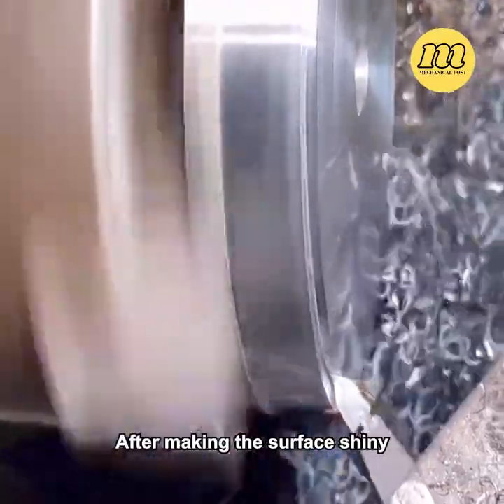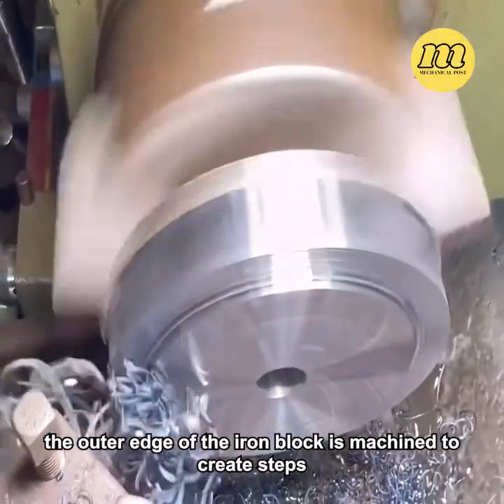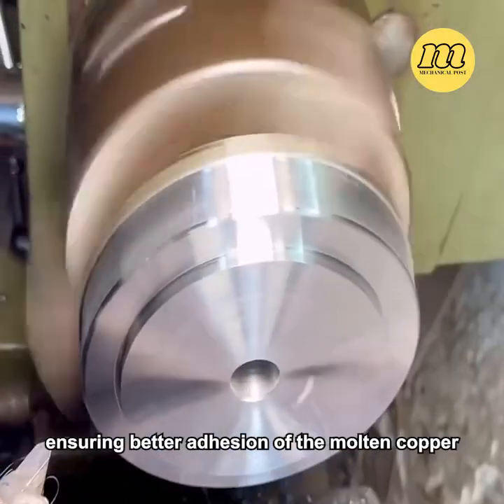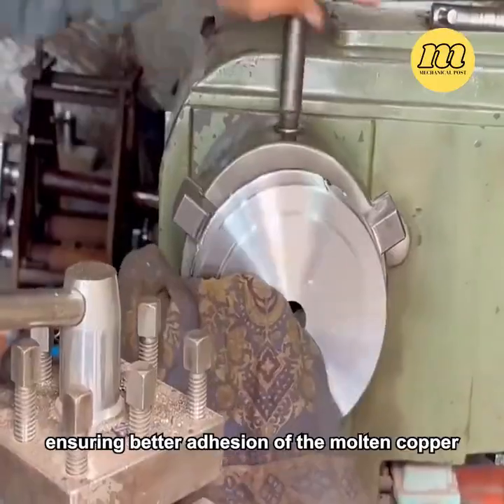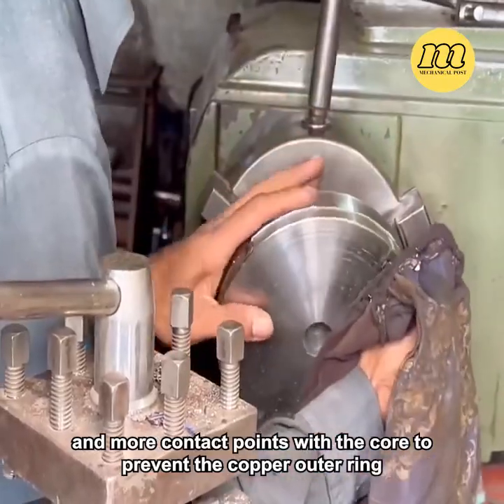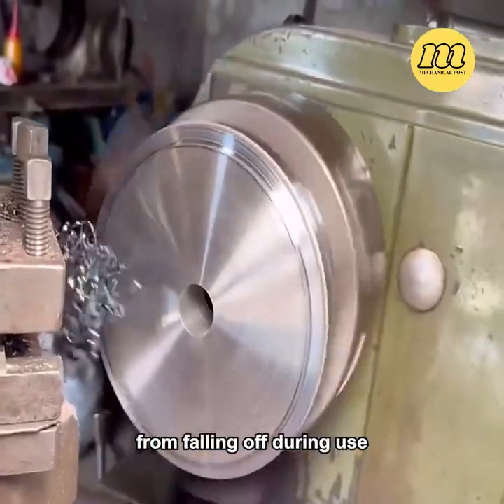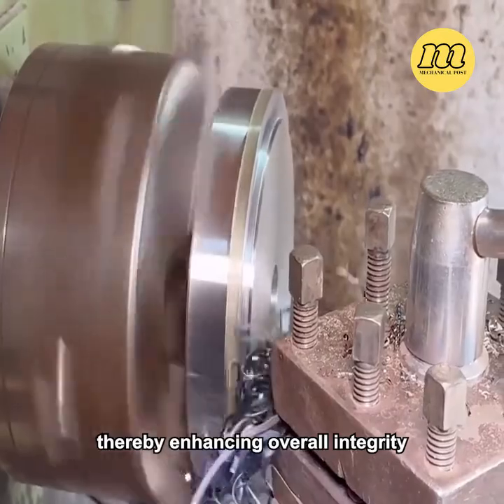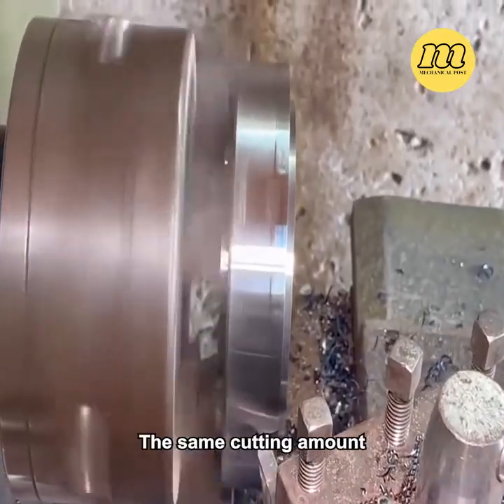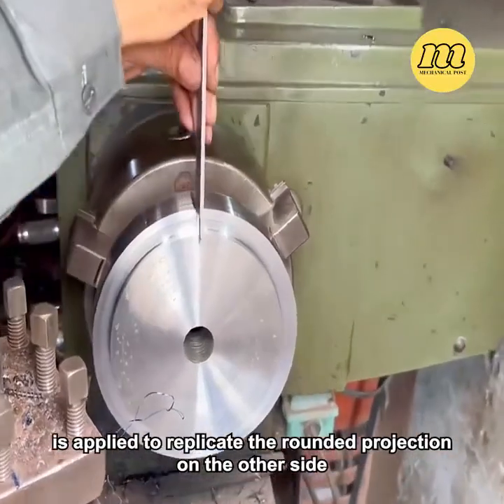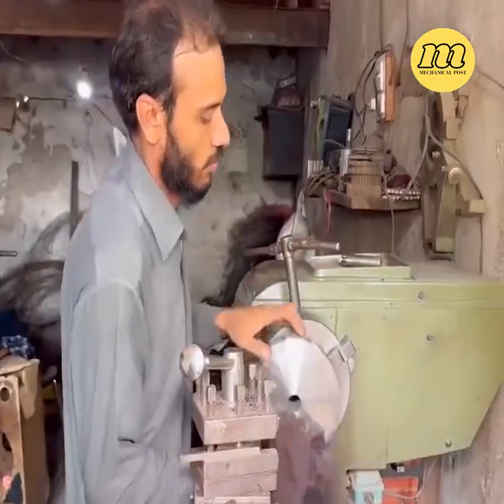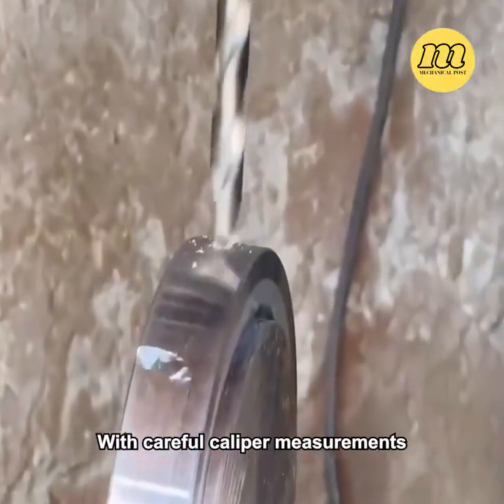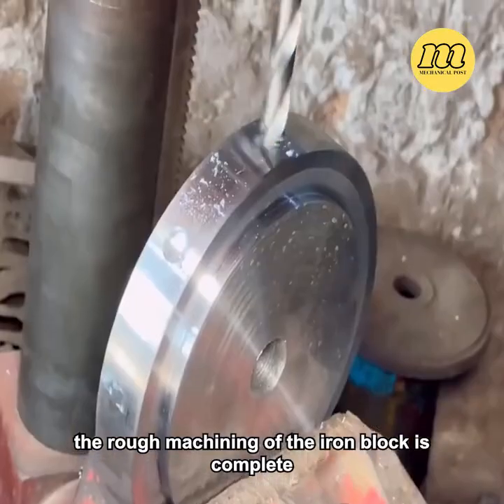After making the surface shiny, the outer edge of the iron block is machined to create steps, ensuring better adhesion of the molten copper and more contact points with the core to prevent the copper outer ring from falling off during use, thereby enhancing overall integrity. The same cutting amount is applied to replicate the rounded projection on the other side. With careful caliper measurements, the rough machining of the iron block is complete.